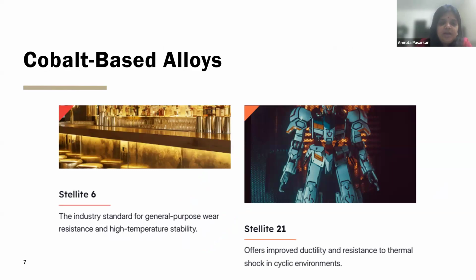Cobalt-based alloys are Stellite 6 and Stellite 21. I am talking about this specifically for 316LN stainless steel base metal. If the base metal is something different, then the powder alloys or the coating can be done with any other material also. But I am talking specifically about 316LN stainless steel as the base metal. So there are two cobalt-based alloys that can be used, Stellite 6 and Stellite 21. These are used for general purpose wear resistance and high temperature stability. This also improves the ductility and resistance to thermal shock in cyclic environments.